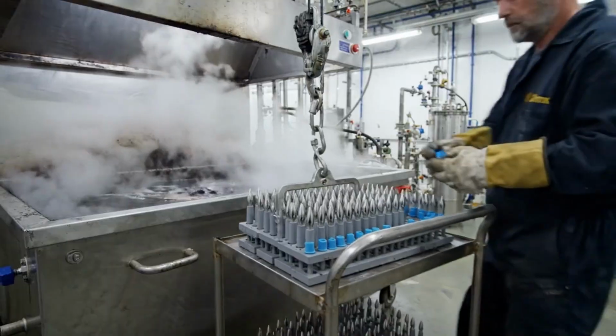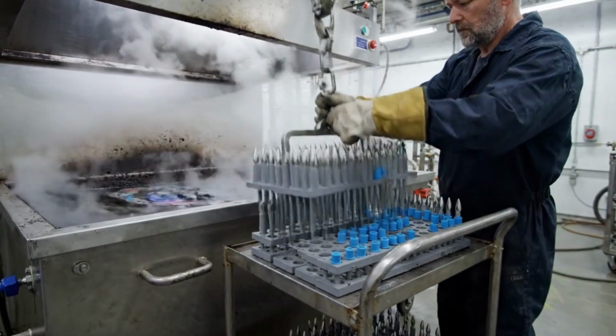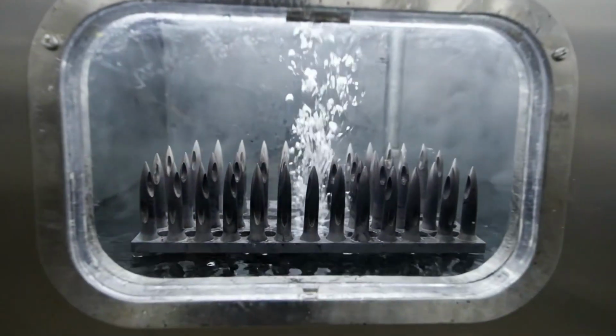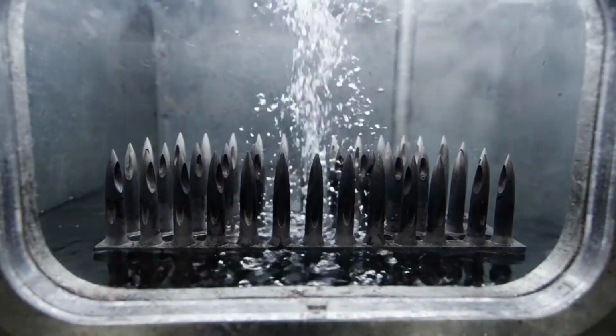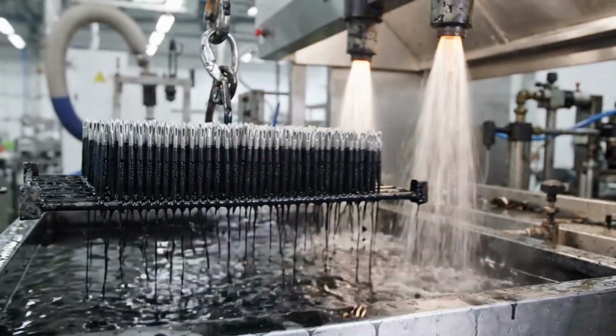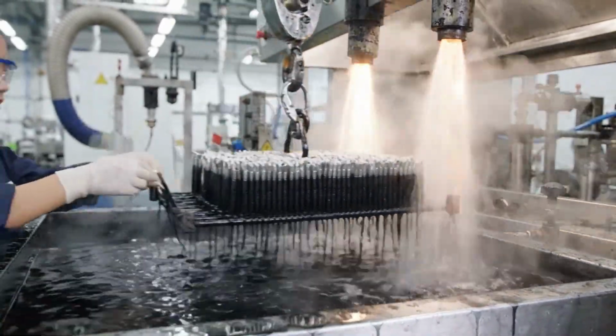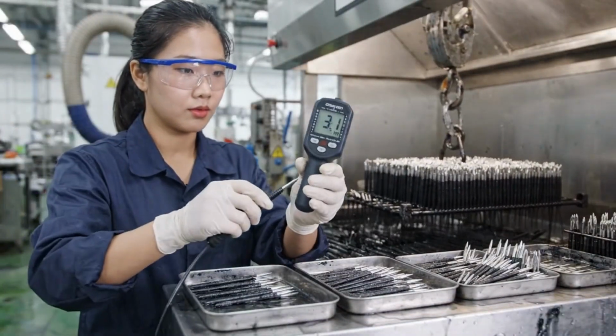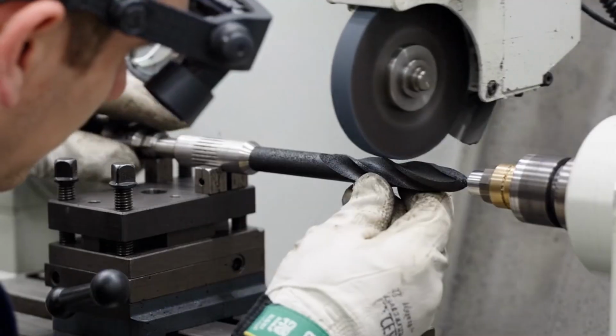The magnetite layer grows to 3 microns thick in 8 minutes. It is not added but converted from the steel itself. The magnetite thickness is measured on every needle. If the layer exceeds 4 microns, it will spall under the repeated impact of the barb.